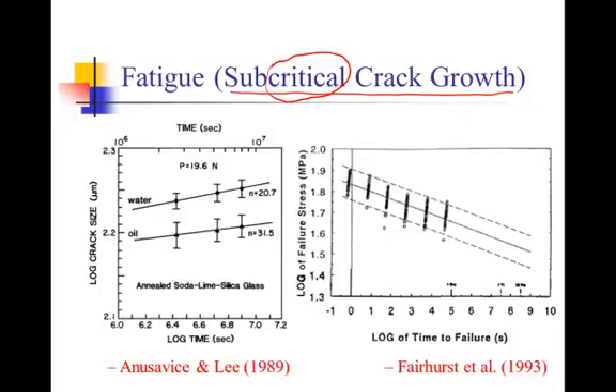And they also noticed that the cracks grew faster when they were in water than when the material was in oil. So a wet environment, such as the environment in the oral cavity, leads to faster subcritical crack growth and shorter lifetimes for ceramic materials.